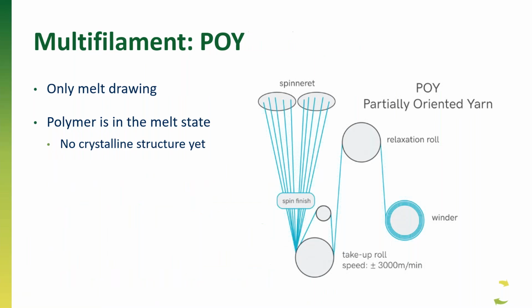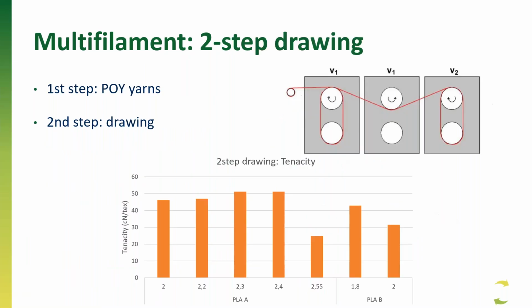This is again written into the CWA, really the process of how to produce these bio-based materials and how to create stronger and better bio-based materials in composites. In the POY process, we are not fully drawing the yarn, but we are only using melt drawing in this step. So only one roll and one relaxation roll. The polymer is still in its molten state and has no crystalline structure yet. We do it at very high speeds, up to 3,000 meters a minute.